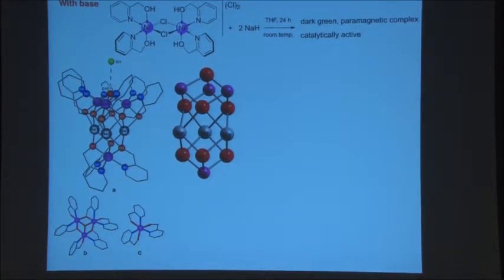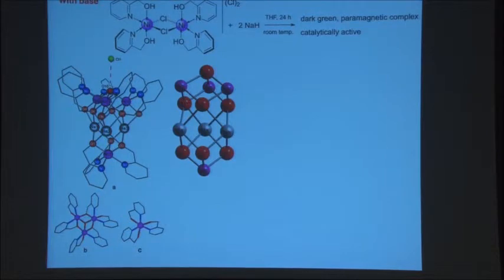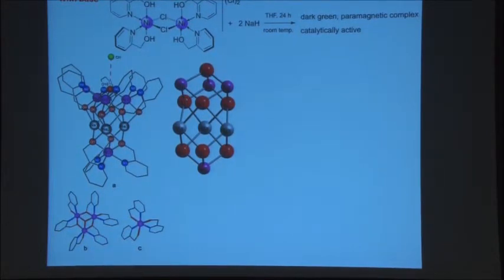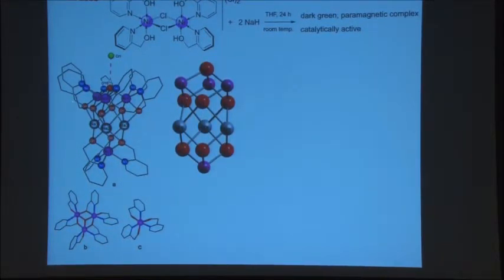This is a complete view of the metal core plus the ligands chelating the nickel center. The blues, the nitrogen of the pyridine, the reds, the oxygens from the alcohol function. And here is the core without the ligands around. So what do you see? An oxygen, 3 nickels, 3 oxygens, 3 sodium, 3 oxygen, 1 nickel. So the 3 nickels on the top here, they are part of a sort of incomplete cubane type structure. You've seen the cubanes before. We have here an incomplete cubane.